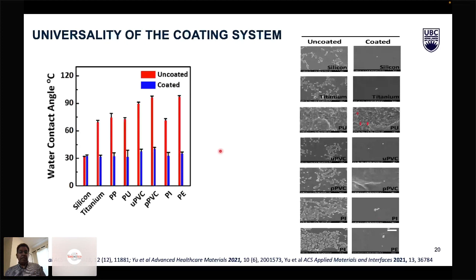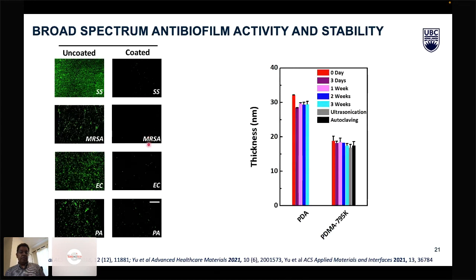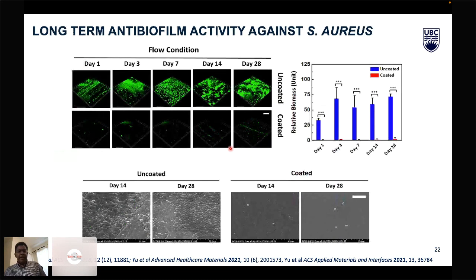And we further looked at different types of bacteria, Staph aureus, MRSA, E. coli, in this example, and we have also seen that it's a very thin coating. And remarkably, this particular coating is very effective in preventing biofilm formation over long periods. The example shown here is in a flow condition. Every day, we challenge the modified surface in a flow loop, and every day we change the bacteria culture.